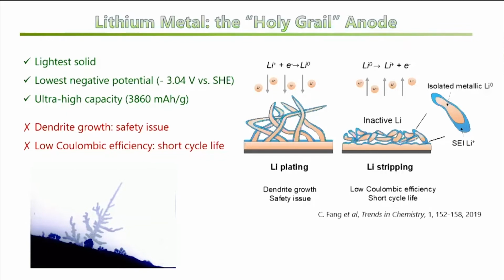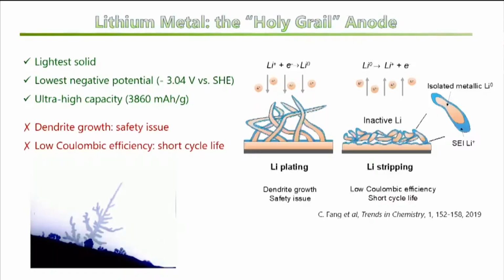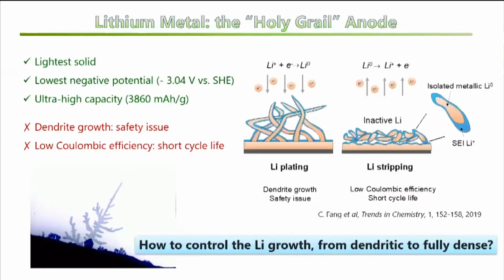That's not applicable. So actually, my group focuses on addressing those most challenging problems associated with lithium metal in order to enable their practical application. We were able to identify the key problem to be solved from a whole complicated failure mechanism. That is, how can we control the lithium growth from dendritic to fully dense?